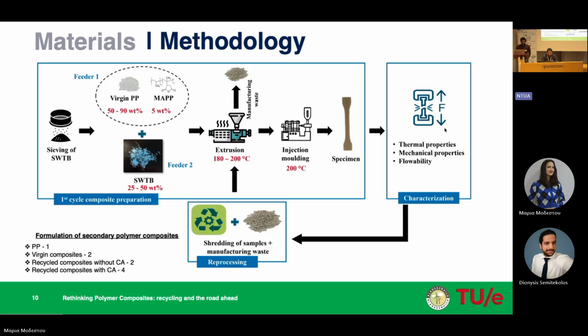And this would be fed into a twin screw extruder, and after the extrusion process, we get the pellets out of it, which will further be used in injection molding to produce all sorts of specimens with different compositions. And later on, I've characterized these specimens to analyze different properties such as thermal properties, mechanical properties, flowability, and whatnot. And later on, the same composites will be shredded again and fed into the extruder in order to reprocess these composites for two more reprocessing cycles.